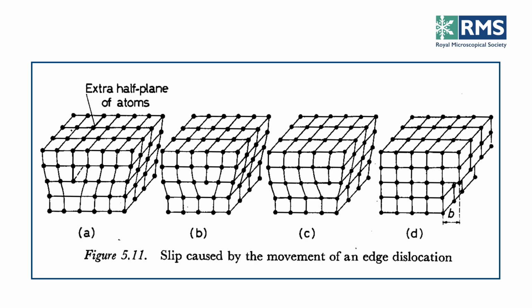I've got a picture of what a dislocation is and what it does. This is called an edge dislocation, and it's characterized by an extra half plane of atoms terminating in the crystal, and you get distortions around it. And these dislocations move by one atomic plane after another, and eventually come to the surface and produce a step, and therefore change the shape of the crystal, and so the dislocation produces the plastic deformation by this slip method.